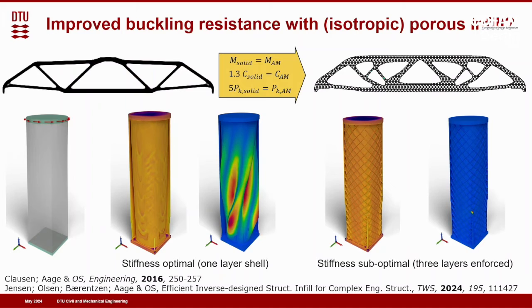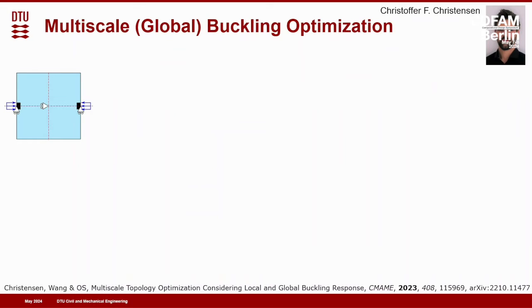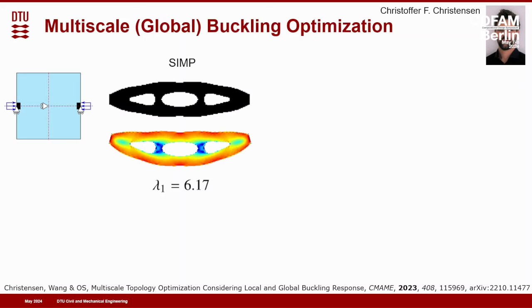But these were lucky punches. We cannot always be sure, and actually the top structure, the 2D lattice structure, didn't fail by global buckling, it failed by local buckling in the lattice structure. So this means we have to actually include that in the optimization. Let me show that. That's work by another PhD student, a very simple buckling example. We have compression horizontally from both sides of a box. If we do standard topology optimization for buckling resistance, we get a certain buckling factor, 6.17. Here we didn't allow microstructure. Then we said, okay, now we allow microstructure, and it can grade the microstructure, but it's a triangular isotropic one.